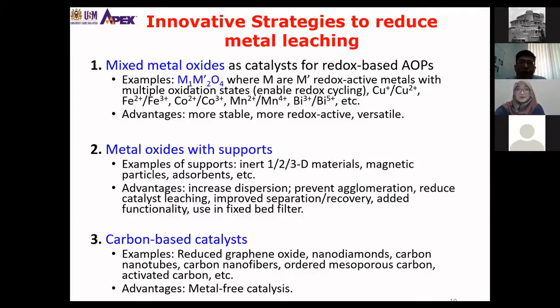In fact, sometimes you can have bifunctionality in mixed metal oxides. For example, if you use cobalt oxide, it's not magnetically separable. But if you convert it into copper ferrite, it becomes magnetically separable, which means that you can use a magnet to remove the catalyst after treatment.